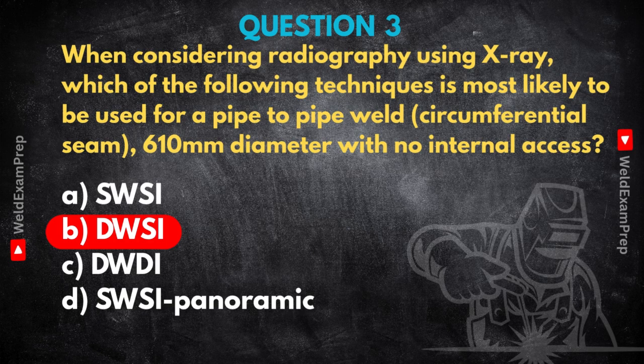What about DWDI? DWDI, double wall, double image. That's really for much smaller pipes, maybe up to about, say, 90 or 100 millimeters in diameter. Yeah. With DWDI, the radiation goes through both walls, and you actually see two images of the weld, one laid over the other on the film. It can be tricky to interpret, and it's just not practical for inspecting the entire weld on a large pipe like this. And the panoramic one?